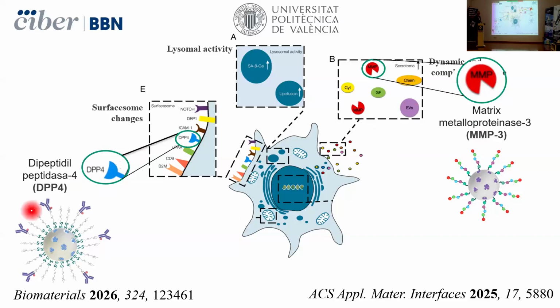So that one, the nanoparticles target a receptor that is overexpressed in some senescent cells, the DPP4 receptor. So this is a mesoporous silica nanoparticle loaded with a senolytic and capped using a polyethylene glycol. And at the end of the polyethylene glycol, we have an antibody that targets the DPP4 receptor. And the polyethylene glycol is attached to the surface using a disulfide bond. So inside the cells, there is a high concentration of a reductor that is glutathione. Glutathione breaks the disulfide bond and induces the delivery of the cargo inside the cells, not outside the cells.